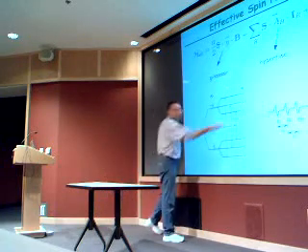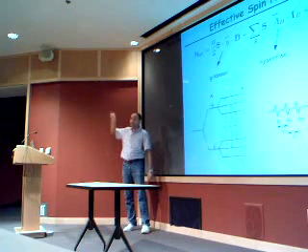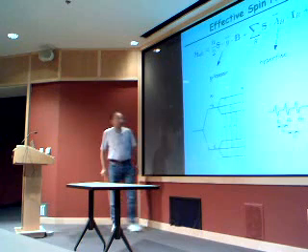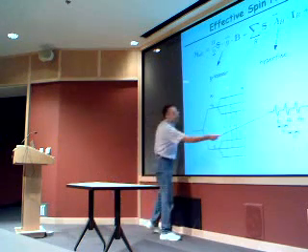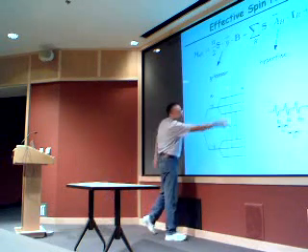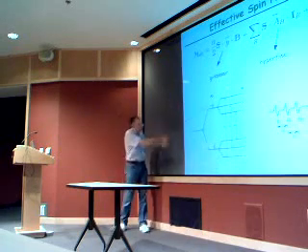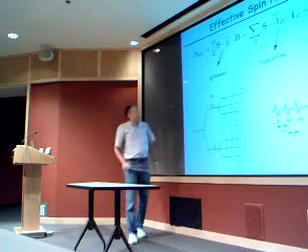This will give you an absorption spectrum with three peaks. The derivative of three peaks is this curve here. Imagine you have three Gaussians, then you take the derivative, and you get this funny-shaped curve. The distance between, let's say, the peaks here is the hyperfine coupling, and the absolute position of the middle line gives you the g tensor, because it gives you this transition energy. Okay, so those are the selection rules for local absorption.